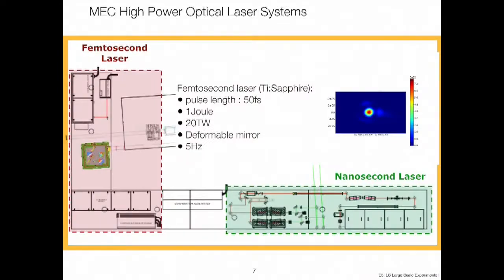The short pulse system is a fairly standard titanium sapphire laser system with a pulse length of around 50 femtoseconds and a total energy of 1 joule. So this gets us to about 20 terawatts. It runs at 5 hertz, and it has a deformable mirror, so the spot sizes you can create are fairly close to diffraction limited, typically with a Strehl ratio of about 0.7, 0.8. There are upgrades planned for this to go to much higher energies, but right now this is what's readily available for users.